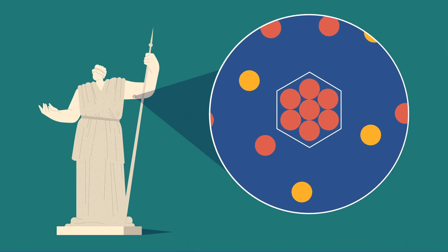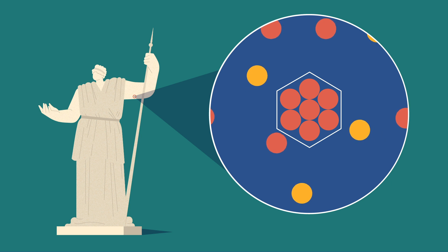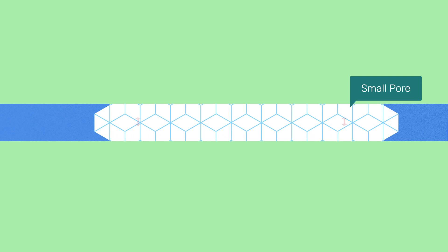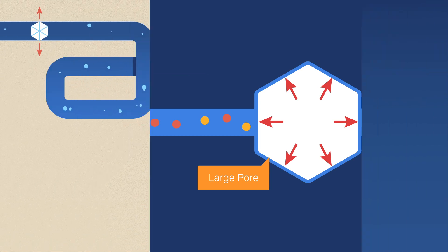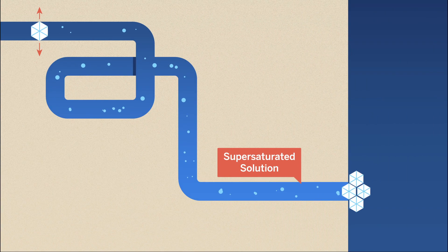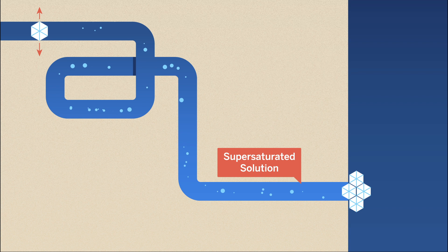It is developed when a crystal tries to grow in a supersaturated solution present in porous medium but encounters some kind of resistance to its free growth, such as a pore wall. Similarly to freezing, this may involve crystal growth in small pores, typically below about 100 nm in radius, filling of a large pore linked to a smaller pore supplying a supersaturated solution, kinetic limitations inhibiting unrestrained growth outside of the material or in large pores, not yet filled by the crystals.